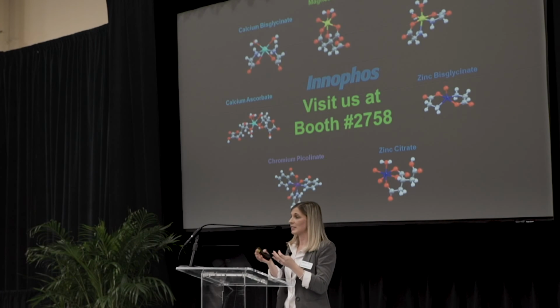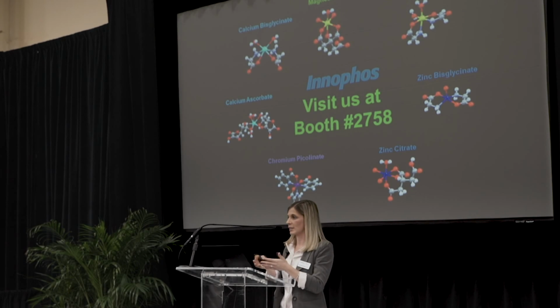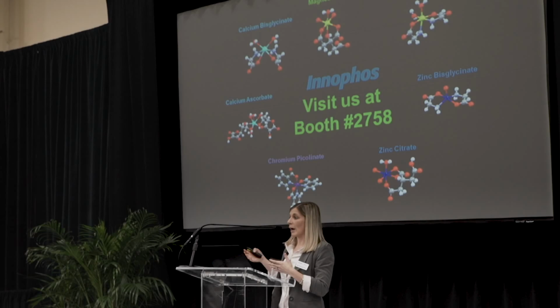Like you're saying, that's a very difficult thing to follow in the body, right? You'd almost have to do isotopic labeling to see that. And there have been some of those studies in rat models. But the other point is then looking at the absorption in general to see if it's not released, then it won't get absorbed. Because there've been studies with phytate and EDTA where there's no increase in absorption by using those materials. So clearly it doesn't let go. Whereas with the glycinates, the citrates, there is increased absorption, so they have to let go at some point in that process.